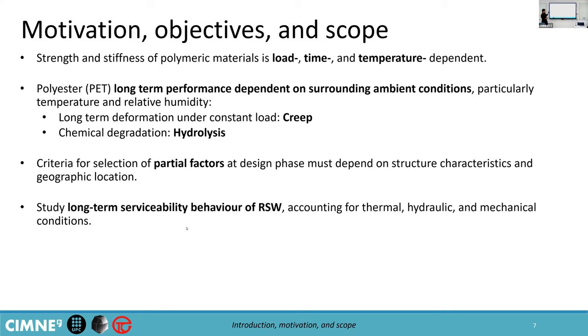In the case of polyester, which is our focus, we have hydrolysis — the degradation of the material when in contact with water molecules, be it vapor or liquid. All of these components are usually incorporated at a design base by partial factors in a commonly consensus as an outward conservative way. Reinforcements have their ultimate tensile strength reduced to approximately 30 to 40 percent for an allowable strength when designing, which is a considerable reduction.